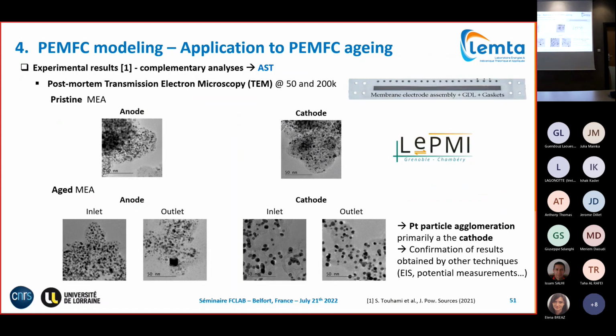And this was confirmed as well by post-mortem analysis from our colleagues at FCLAB, who analyzed the MEAs that we used for our tests, by transmission electron microscopy analysis here at the anode and the cathode. In light gray it's the carbon particles, in black and dark gray it's platinum, beginning of life and end of life, and we see clearly at the cathode platinum particle agglomeration, which confirms that we have carbon corrosion and platinum dissolution or agglomeration. But if you look at the anode, there's almost no dissolution. So this confirms that electrochemical processes should not be at the origin of this degradation.